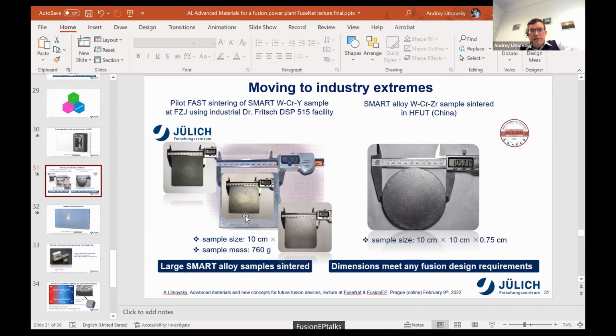It is an industrial facility. The entire duration with the cooling was, if I remember correctly, 20 minutes with cooling. Full automatic process at the end. So you're basically pouring this die with the powder, and then you're getting the sample which can be ground. I do not see any obstacles of making, instead of this industrial facility, 10 of them. They will cover square meters in one day, and we have to achieve around 1,000 square meters. A couple of months, I would say.